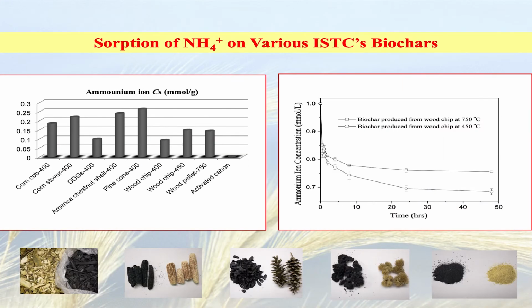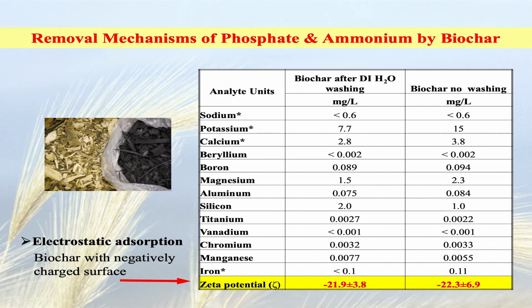So this is my lab. We produced different biochar from different biomass. You can see for all the biochar, compared to the activated carbon, our biochar can successfully remove the ammonium ion. After measuring the zeta potential, we saw that for most biochar the surface is net negative charge, so they have strong absorption of the cationic chemicals, for example, like ammonium ion, through the electrostatic absorption mechanism.